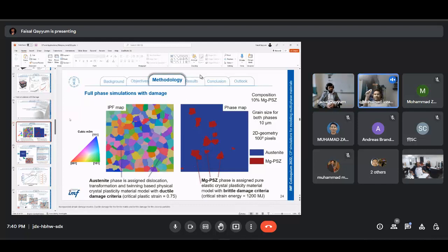So once initiation starts, then it will choose its direction, right? It will choose the direction that it's based on. Yes, based on which next voxel has the next maximum principal strain. And that maximum principal strain is basically depending on the orientation, phase, overall deformation behavior, and then applied load, and many other things which we define. So if all those conditions are met, the maximum principal strain is achieved, then the damage will propagate in that direction, or it will not. If you have only a 2D RVE, it's just like 360 options of direction, right? It will choose. But if you have 3D, it means you have like spherical. Yes.